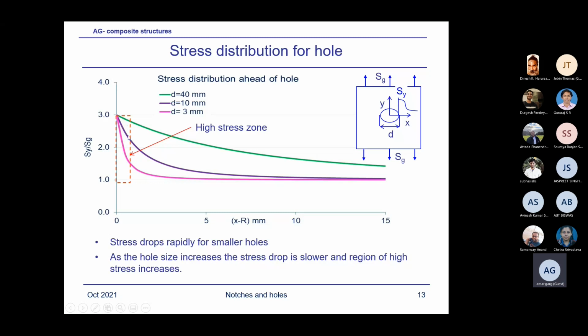So what you are seeing here, if you have a larger diameter of hole, then a larger portion ahead of the hole edge is under high stress. So this is higher stress compared to the smaller hole. This is why I've said, okay, high stress zone, because this region is of a high stress here. But the stress gradient is very sharp for the smaller holes. So for small holes, the stress drops very rapidly from the edge of the hole compared to the larger hole.